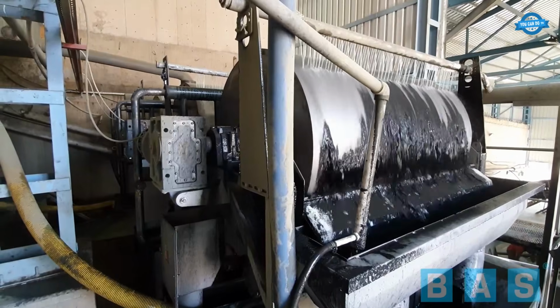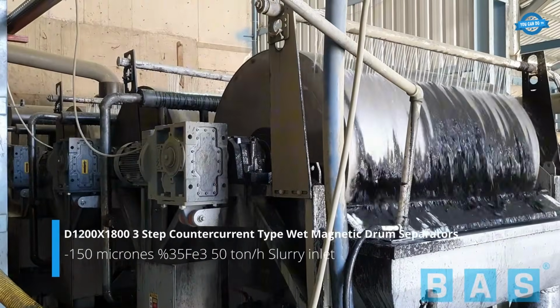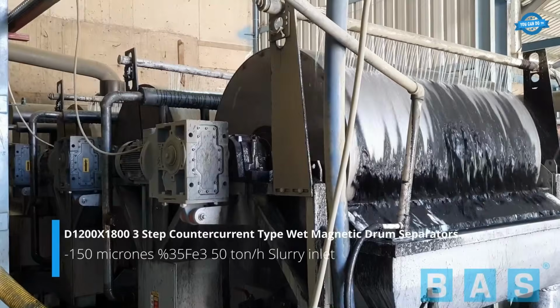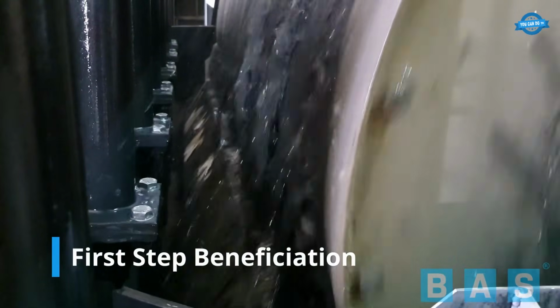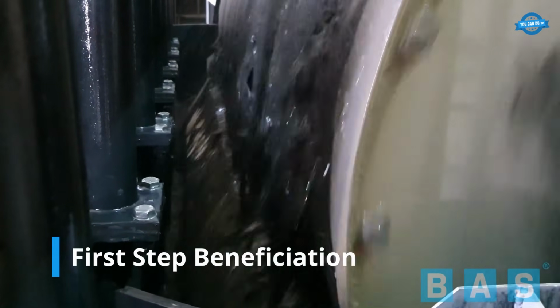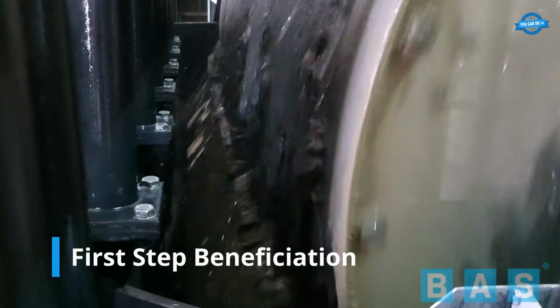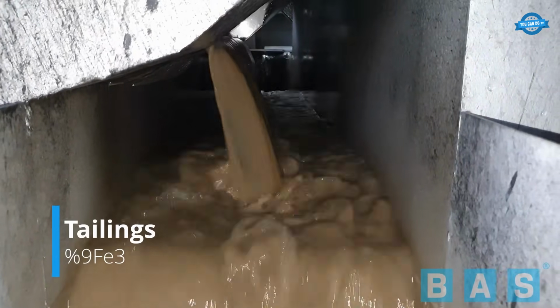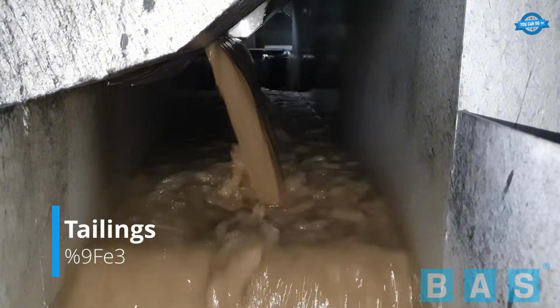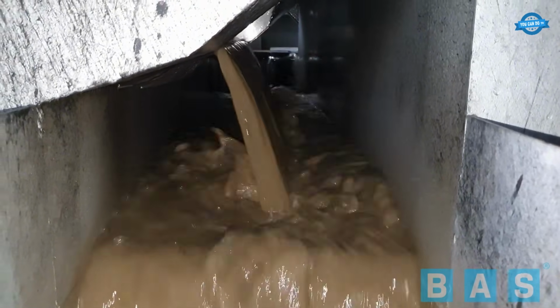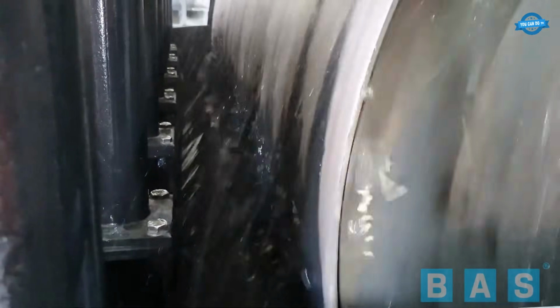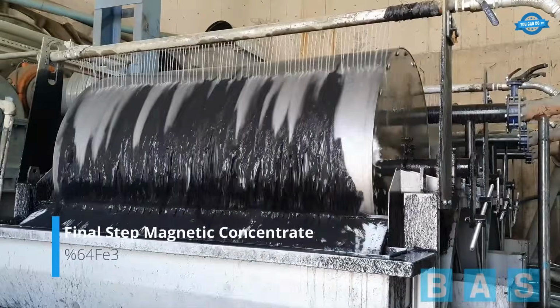And when the ore particles are already ground finer than beach sand, the whole approach shifts to wet magnetic drums. Slurry pours across a rotating drum with a magnet inside. Magnetite grains cling to the surface like they owe it money. Everything else washes away. 3 stages take the feed from 35% all the way to 64%.